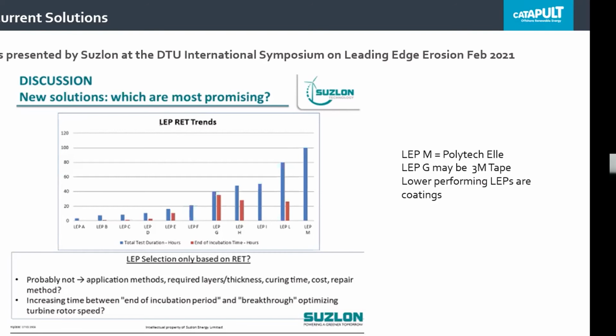Your tape materials can perform really well in the rain erosion test, and I'll show you in a couple of slides, perform really badly on a wind turbine. But the leading product, as I said, is the Polytech Elle, which is LEP M. Here they show it as lasting 100 hours before failure. ORE Catapult have just finished testing, probably at a lower rotational speed, and it lasted 160 hours.